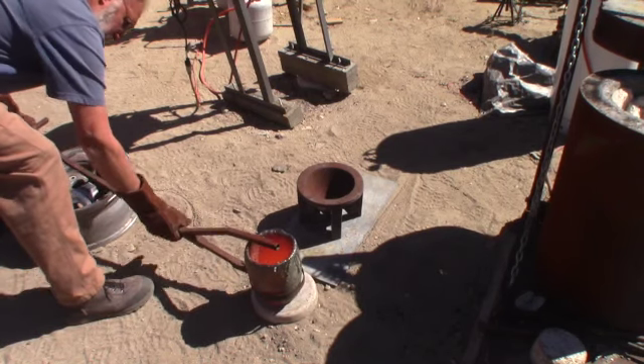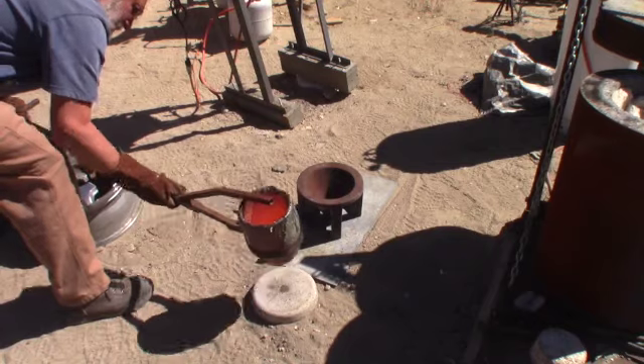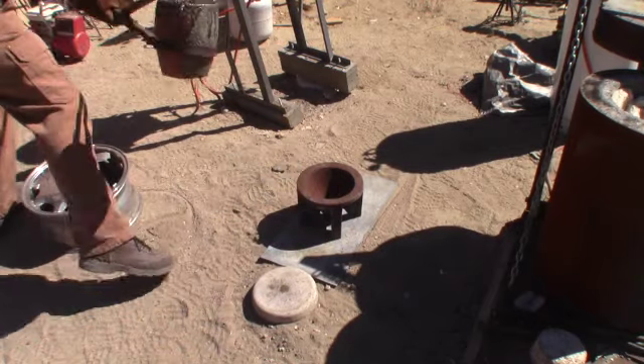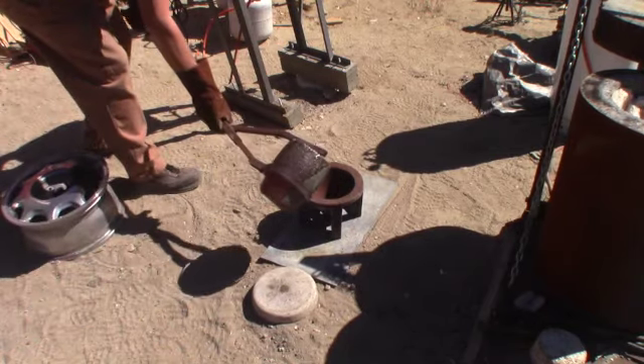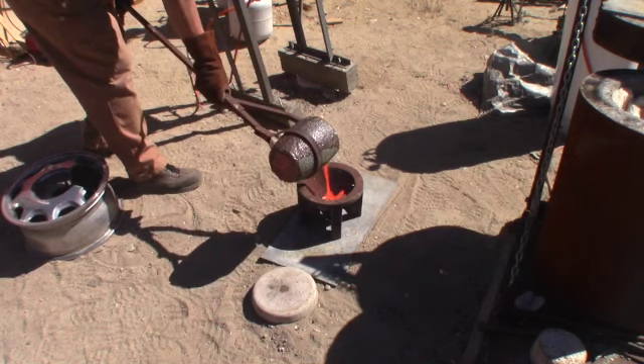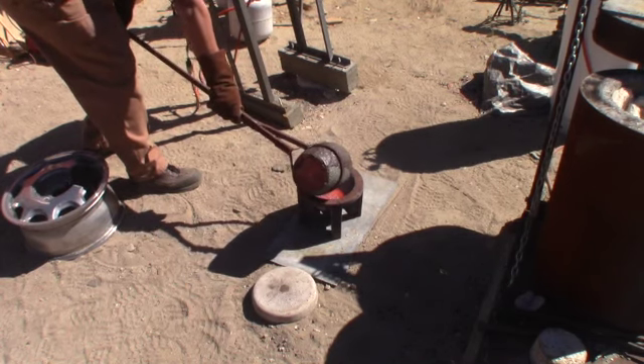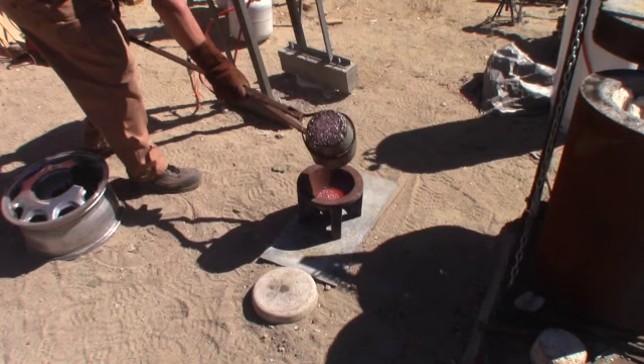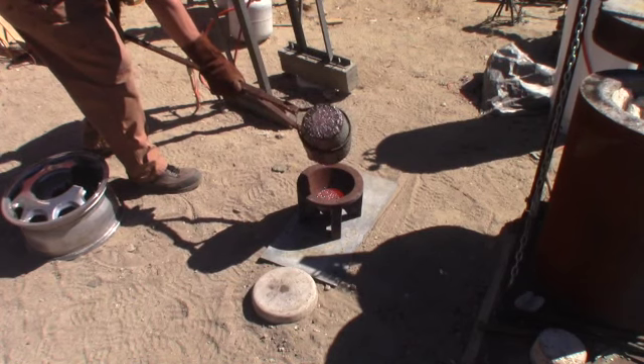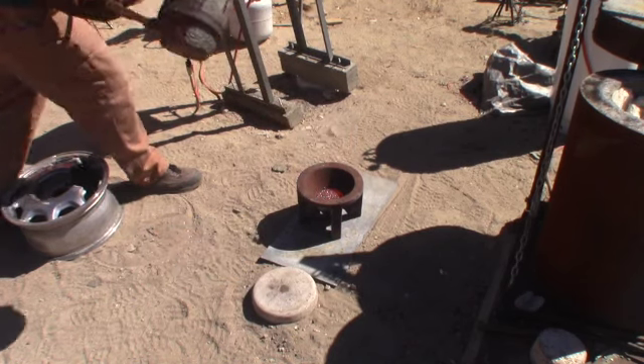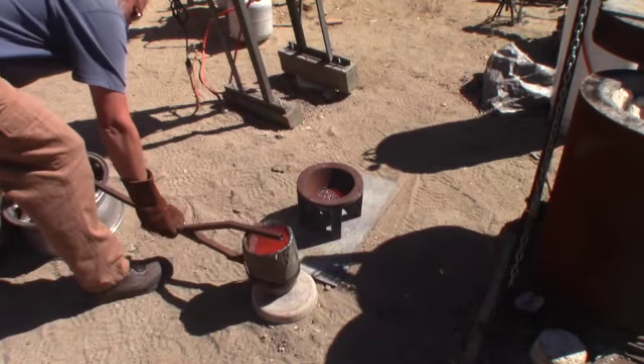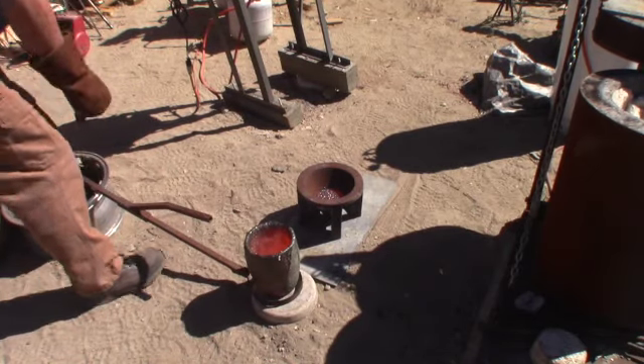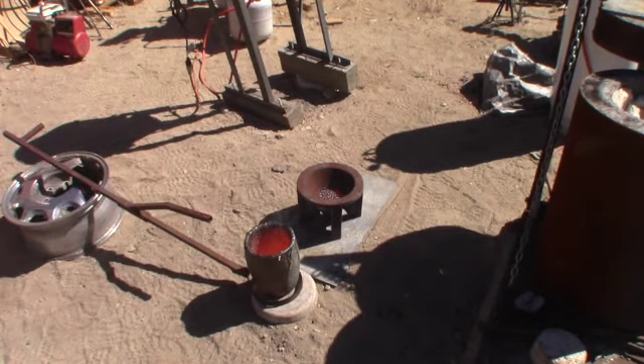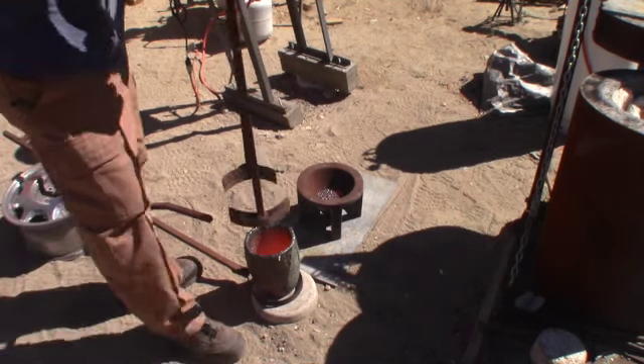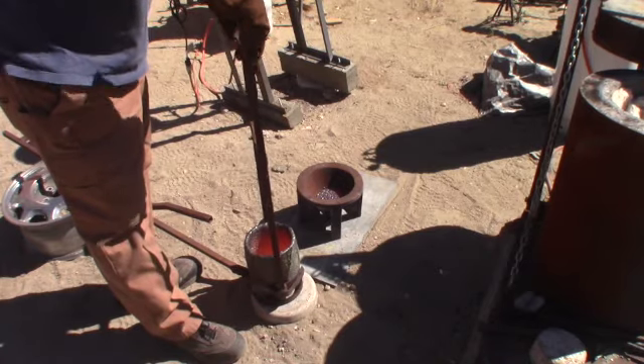And we pour it into a cone-shaped mold. Now the purpose behind this cone-shaped mold is we've added some lead to the smelt, and any of the fine gold particles will hopefully glom together with the lead and settle to the bottom. Pouring it into the cone-shaped mold, you'll wind up with a little conical-shaped biscuit on the end that should have all your precious metals in it.